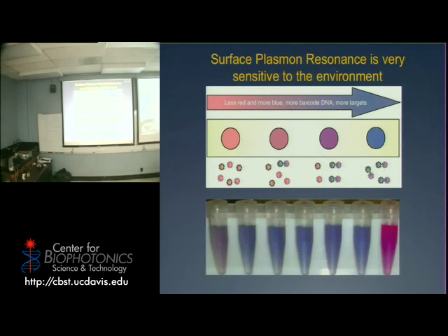What happens is that when you increase the ionic strength of the solvent, they're stabilized electrostatically, remember? These guys are negatively charged. The only reason they're separated is because if they get too close, there's a big repulsion coming from these 2 negatively charged particles. But if you increase the ionic strength by adding salt, you shield this repulsion. So they have a tendency to aggregate, right?